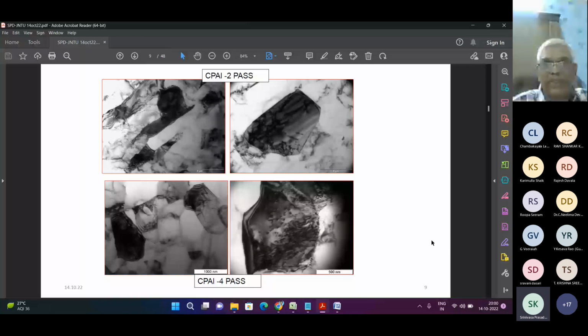It has become... the columnar structure is being changed to an equiaxed grain structure, which is less than 1 micron. You can see that from the micron bar also. This is the work we have done for TEM, and all this work is published. Next slide, please. Yes, sir.